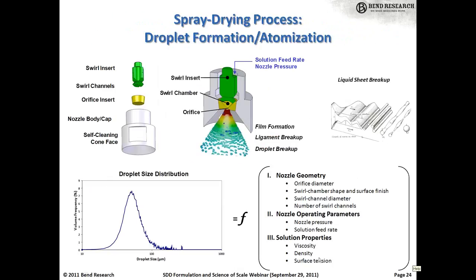So switching gears and looking at the droplet formation or atomization parameters, shown here on this slide is a pressure swirl nozzle that we work with quite a bit for these spray-dried dispersions. This is just one option for atomization in spray drying. You can use other atomization types like two-fluid nozzles, rotary atomizers, or just the straight pressure nozzles. We find that the pressure nozzles have been very easily tunable and scalable, so we work with these quite a bit.